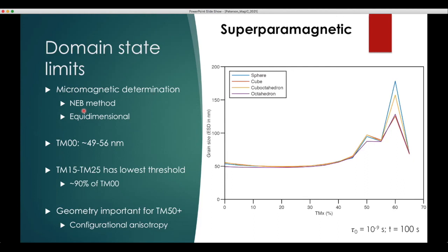Yeah, and I suspect that it's likely to be interactions. So you model single grains, yeah? Yeah, these models are just single grains. So you don't have any interactions. Okay. And there have been studies on SP particles where essentially they have interacting clusters of SP particles that have remanences, and this is a bit of a frontier in nanotechnology to develop magnetic memory devices, so it is entirely possible to see a remanence of an interacting SP particle. Yeah, that much remains.